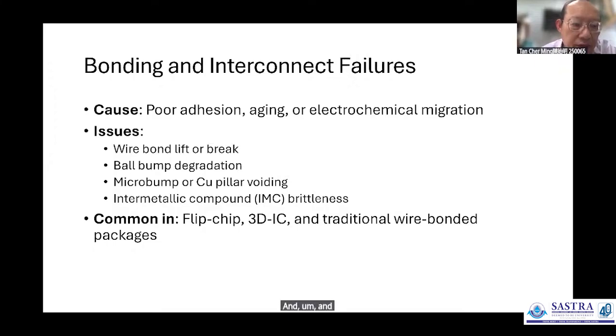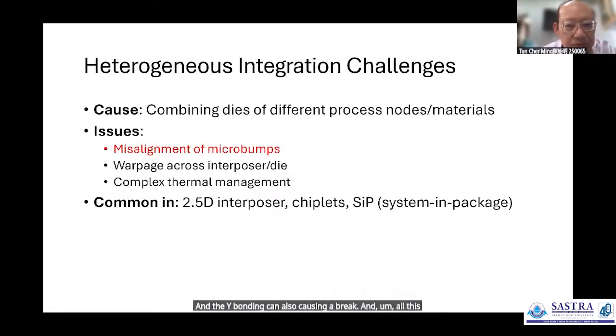And then, as we know, in the chip we have wire bonding, solder bump and also micro bump, and all these will form an intermetallic, as I mentioned before. And the wire bonding can also cause a break, and all this will cause problems. And when you come to heterogeneous integration, we are combining dies of different processes. So when you're putting a die onto the substrate itself, there are micro bumps. The misalignment of the micro bump can be an issue because the dimension is very small. Therefore, the tolerance has to be very good. And also, because of different materials, it can cause warpage if your design layout is not proper.